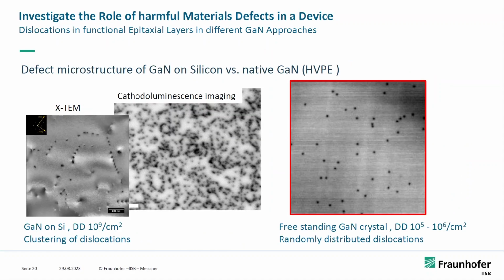Here's a quick insight: cathodoluminescence imaging, which is dark spot counting that you see here. Any of the dark spots stands for a place of dislocation or a bundle of dislocations. Gallium nitride on silicon shows around 10 to the 9 dislocations per square centimeter, while a freestanding gallium nitride crystal shows 10 to the 5 to 10 to the 6 regular dislocations.